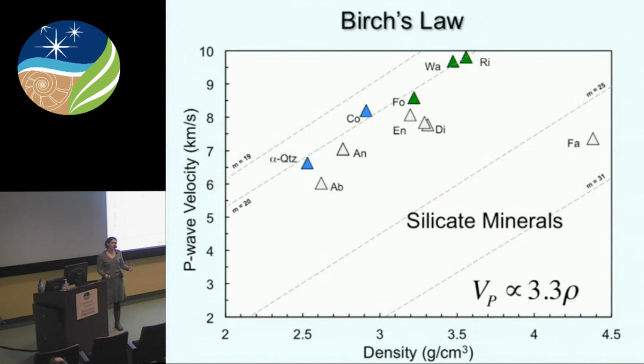Okay, so let's start at Birch's law. So in 1960, Birch published this seminal paper, right, where he measured the compressional velocities of a wide range of rocks and minerals to about a GPa, and what he found is that there is this positive linear correlation between velocity and density for minerals of a constant mean atomic weight. And what that means is, a mean atomic weight is when you take the molecular formula weight and divide it by the number of atoms. So most silicates are actually around 20 for this.